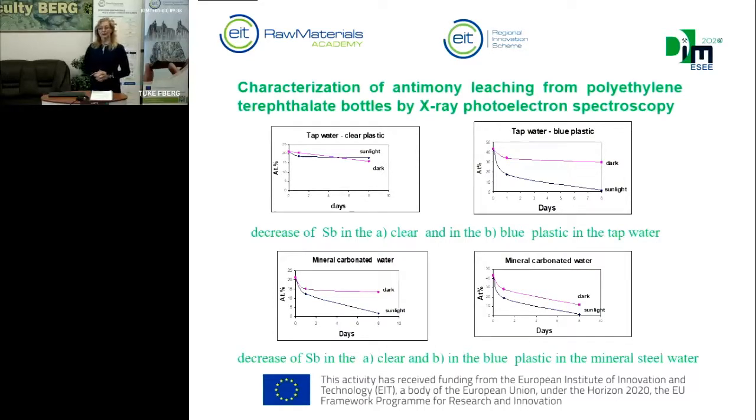We confirmed that the leaching of antimony from blue plastic is more rapid than leaching of antimony from the clear plastic, and the leaching of antimony by carbonated water is more rapid than the leaching of antimony by the tap water.